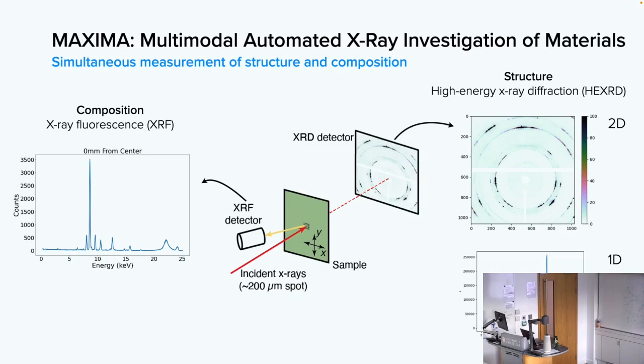This happens to be just a 7000 series aluminum alloy. This particular sample was about 1 millimeter thick. But because of the high intensity of our spot and the sensitivity of our detector, this diffraction pattern was recorded in about 10 seconds. So if we want to do like a 10 by 10 grid on a relatively large sample, we can easily do that in a matter of minutes. All right, so it really is a high throughput technique.